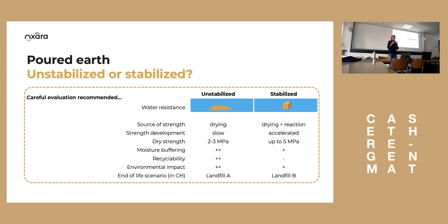And then on the moisture buffering side, the unstabilized one performs better. This is clear because you have purely the water and the clays which can interact with each other. If you introduce a stabilizer, this also binds the water and interferes with this interaction. The same for the recyclability, and there it's a bit more drastic. If you have unstabilized clay, you can dissolve it in water, and that makes it reusable infinitely. If you add a few admixtures, it's a bit of an in-between case. You have an accumulation of these admixtures, but if it's still dissolvable, you can reuse it in the same way as pure raw earth. But if you have the stabilized clay and it binds together, then you don't have that easy way of recycling because it doesn't dissolve anymore.